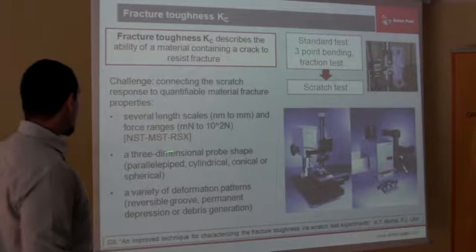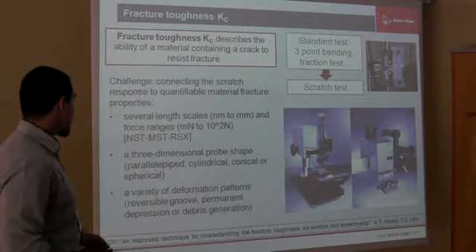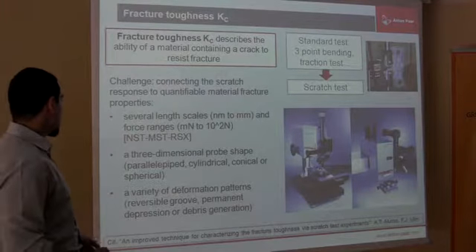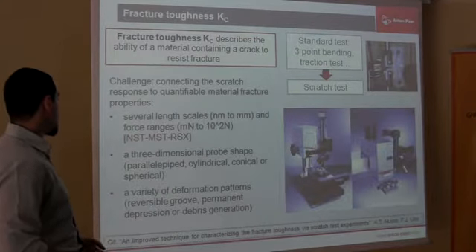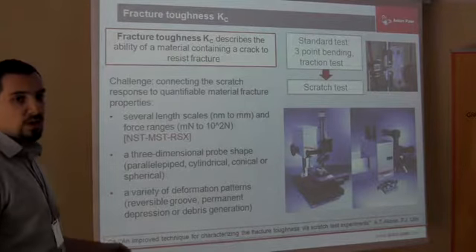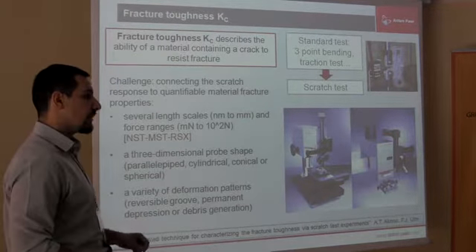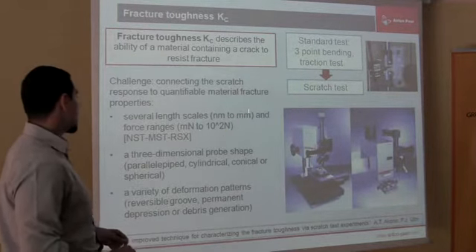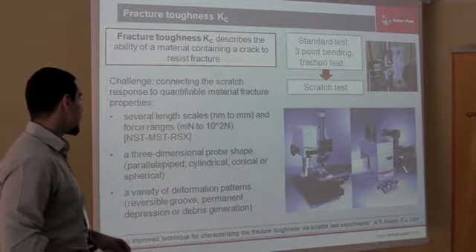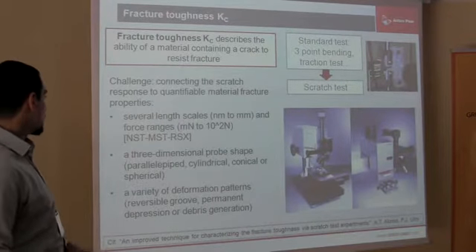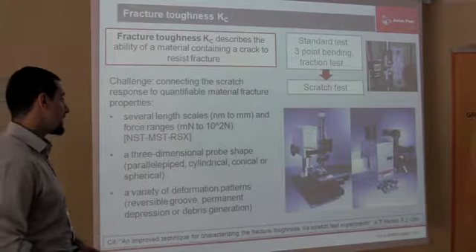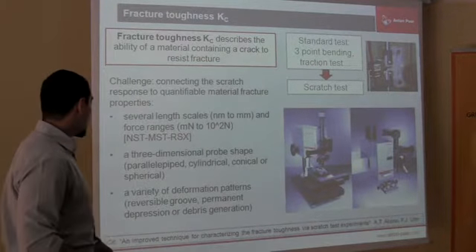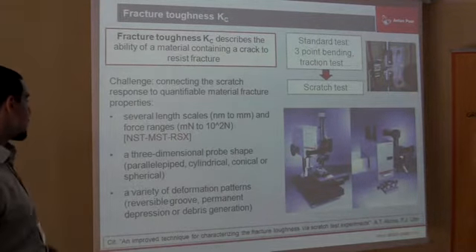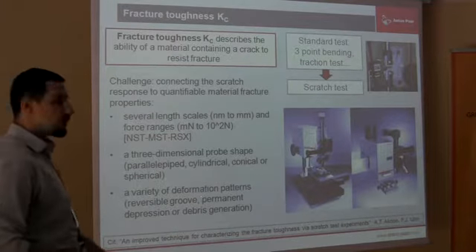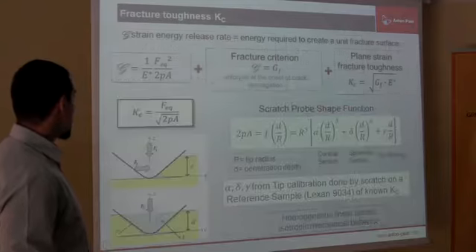This is difficult because with the scratch test we have several length scales, from nanometers with the nano scratch test, which can be used to analyze very thin layers, up to millimeters and high loads, hundreds of newtons, with the Revetest scratch test, which is a macro scratch test. Then we have to face the three-dimensional probe shape and a variety of deformation patterns inside the sample.